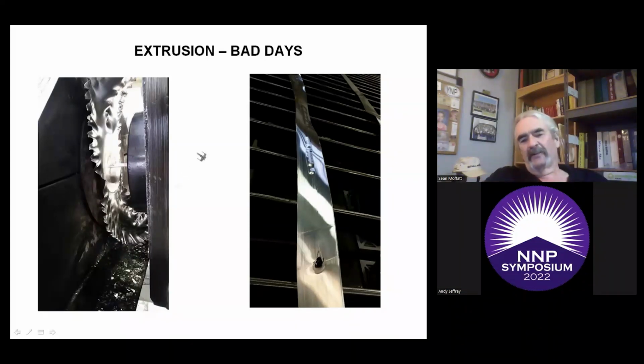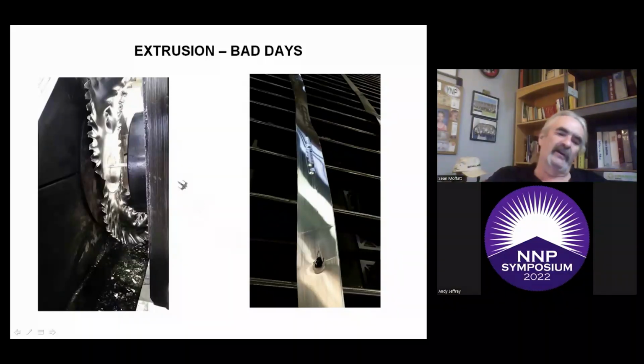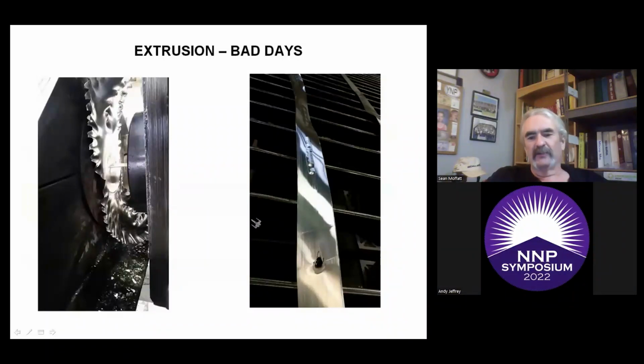And then you can also get garbage that comes out of your melting process. You get a piece of crucible or something mixed in with the metal, and you can try to shove it through your extrusion die, and it gets caught in there, and it'll just blow holes, and then it adds all kinds of impurities, and you see all the bubbles that came up in the strip after that.